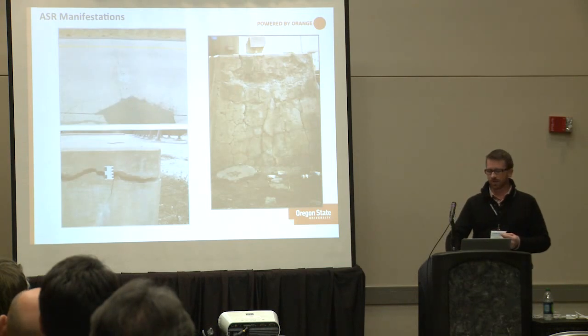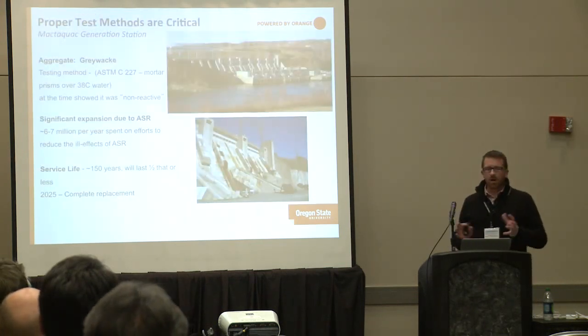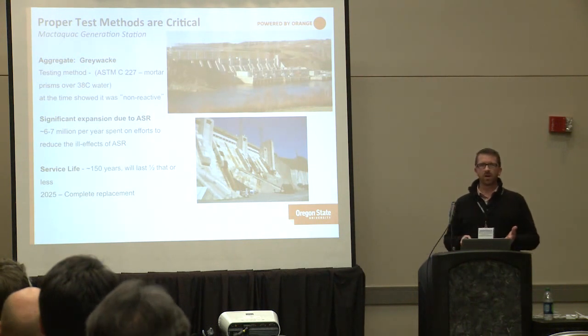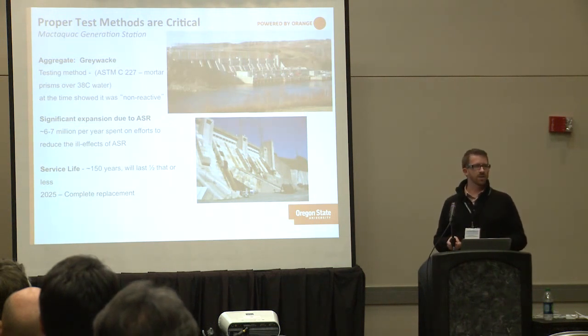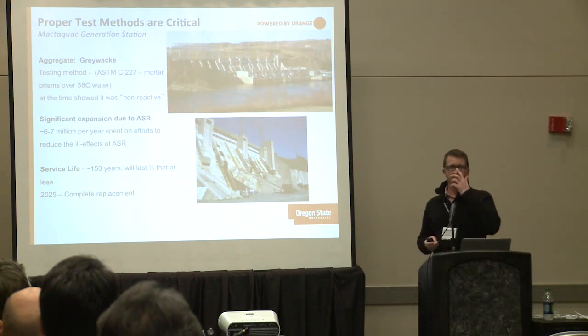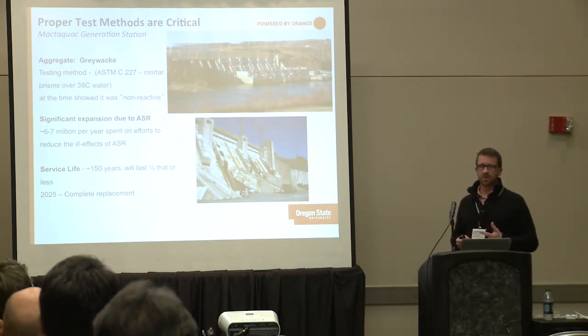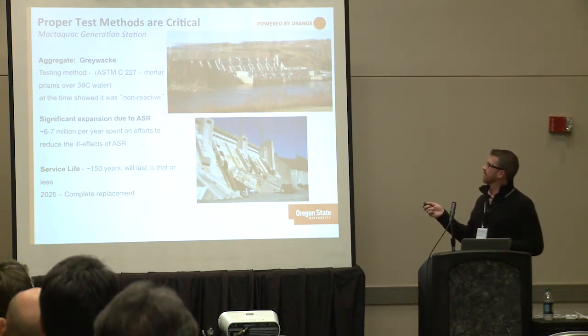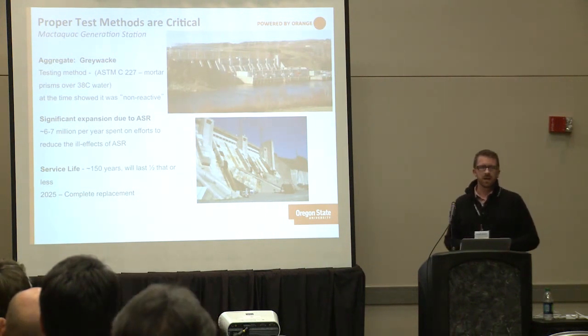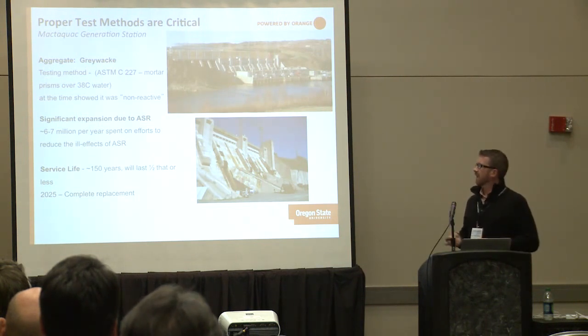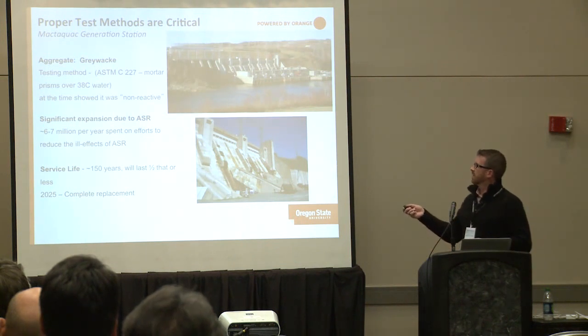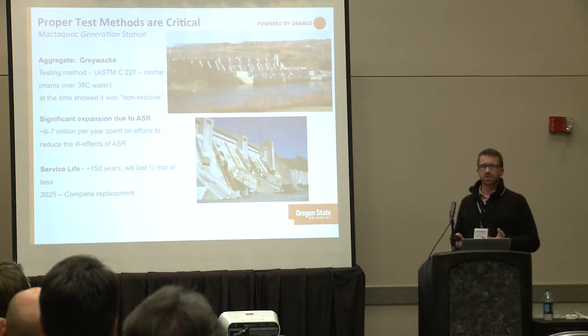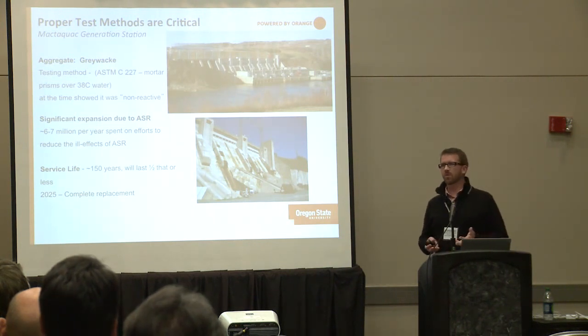Walk away with the idea that proper test methods and knowing what your test method tells you is critical to assessing the potential for aggregate reactivity and mitigation options. I'm using the example of the Mactaquac Generation Station, a hydroelectric dam in New Brunswick, Canada. When it was built in the late 1960s, they used the ASTM C227 mortar test — small prisms, one inch by one inch by eleven and a quarter inch, stored over water at 38°C — to assess the greywacke aggregate.